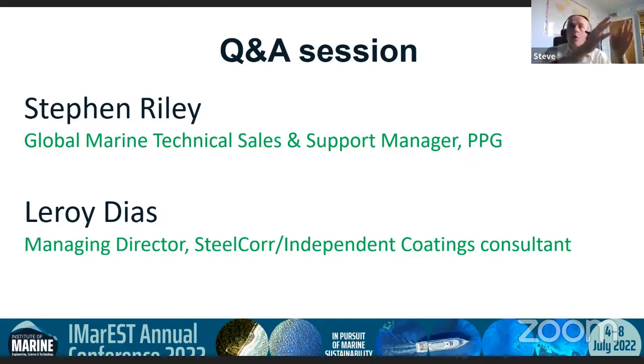And when you come to an antifouling specification, if you say, I want to spec for 2 years, 3 years, 5 years, you see antifouling thicknesses change to cater for that increase in time. With a foul release coating system, if you want it for 12 months or 120 months, it's exactly the same specification. There isn't any change. And DFT, the dry film thickness of the functional top coat, is king, because that's where the release properties are housed. That's the functional top coat. But it functions by being completely inert and having a low surface energy.